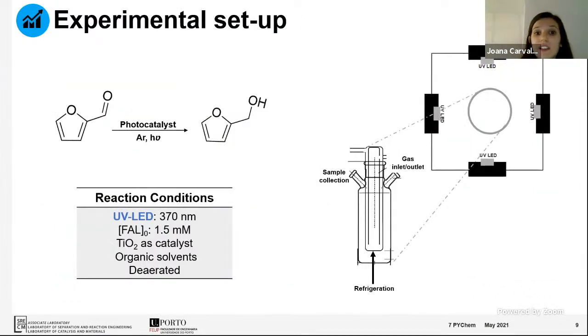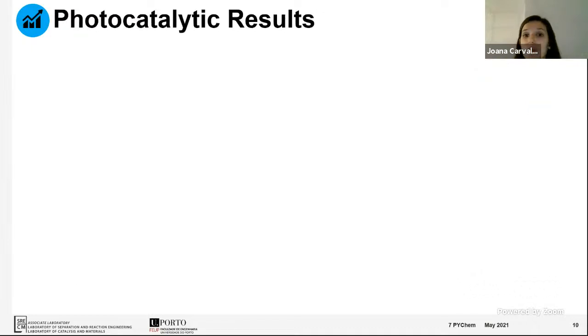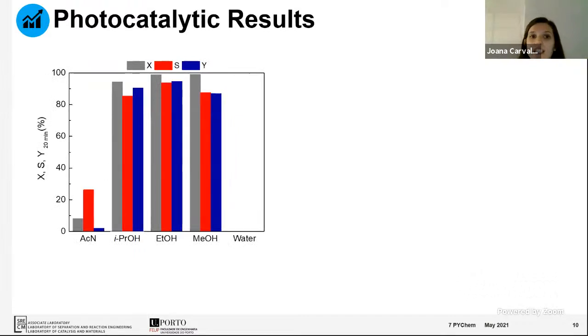All the synthesized materials were tested in the photocatalytic conversion of furfural into furfuryl alcohol. In this case, a batch system with refrigeration was used in order to maintain ambient temperature. It used UV LEDs, organic solvents and anaerobic conditions. To initiate this study, the effect of solvent in this reaction was studied.